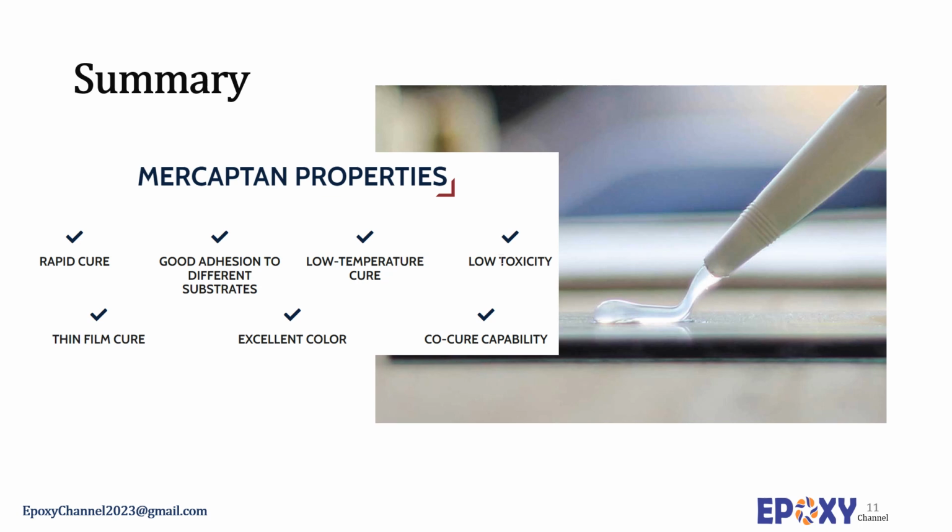Thiols can be combined with other curing agents such as amines, acid anhydrides, and phenols. It is suitable for low temperature epoxy curing systems in combination with a base catalyst. Overall, thiol systems possess fast gel times, forgiving stoichiometry, one-to-one mix ratios, good performance at low temperatures, the ability to bond different substrates, and relatively low toxicity.